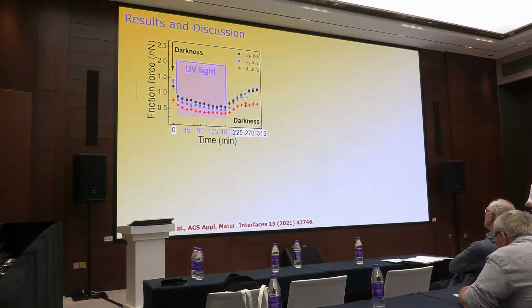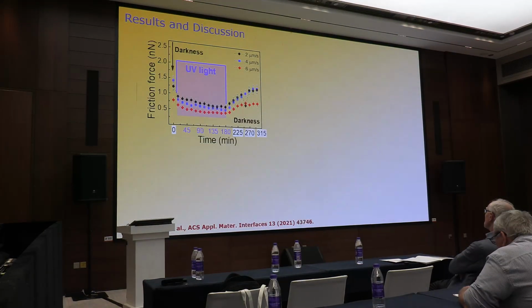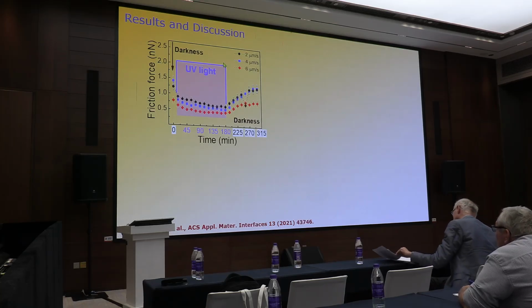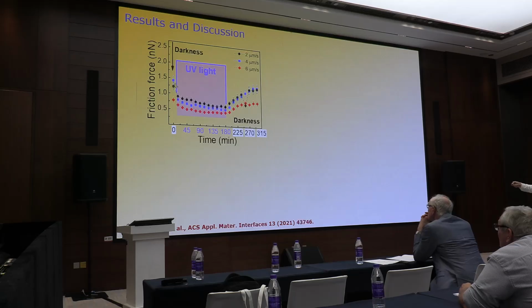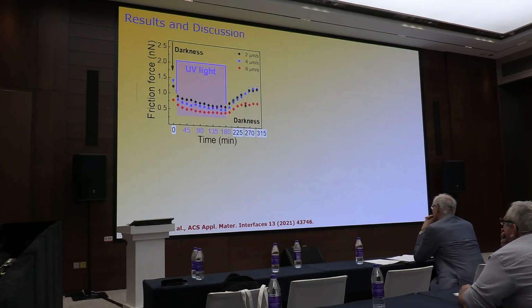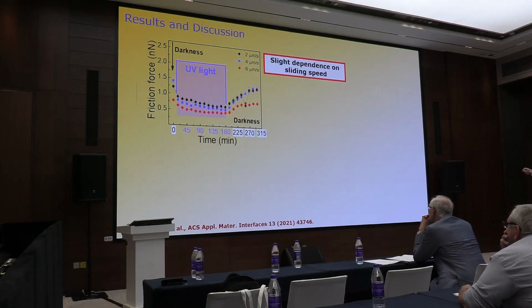Okay, let's go to other experiments. Here you can see different sliding speeds of the tip on the surface, from 2 micrometers per second up to 6 micrometers per second. We maybe have a lower friction force when the speed is higher, but it's not so important. It's a slight dependence on sliding speed, but the most important thing is that when we have UV light, there is a reduction of friction force. This is the most important.